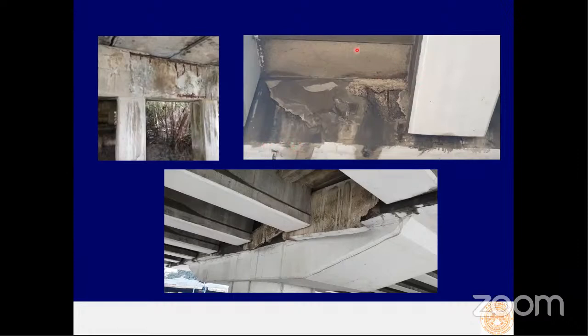that is shown in these pictures and in these pictures. This one is a similar problem to what we found in the short span bridge. We found impact load from the top of the superstructures that caused some micro cracking. And that micro cracking is subject to corrosion because we have the problem of water leakage at the top. So that caused corrosion inside.